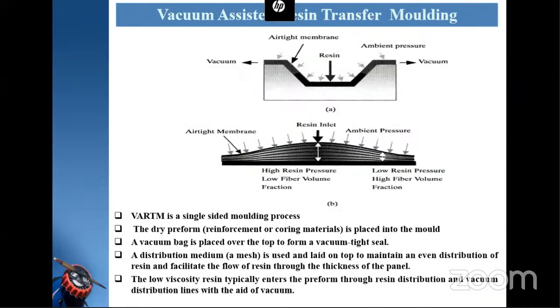There is another important technique which is widely used nowadays, even in the aerospace industry: vacuum assisted resin transfer molding. In this, the mold is made on one side, and on the other side a flexible membrane is used, and the reinforcement is put onto the mold, and the resin is injected from one side to the other side, so that the resin flows all through the reinforcement, and finally you get the composite. This technique is widely used for making large size components like wind turbine blades, and this method is gaining a lot of importance because we can get the components without any defect, and large sized components can also be realized in a reasonable time.